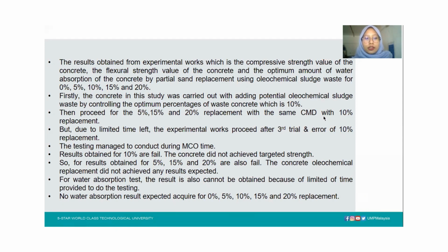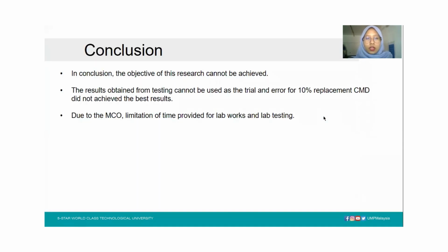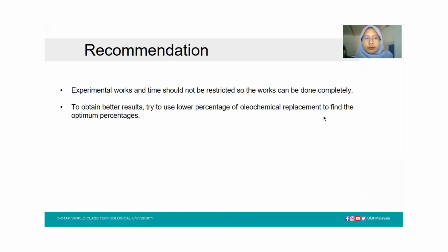For the water absorption test, the result also cannot be obtained because of the limited time provided for lab testing. No water absorption result was obtained for 0%, 5%, 10%, 15%, and 20% replacement. In conclusion, the objective of this research cannot be achieved. The results obtained from testing cannot be used, as the trial and error for 10% replacement did not achieve the best result, due to the MCO and the limitation of time provided for lab works and lab testing.